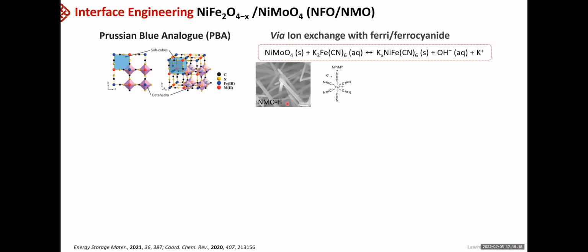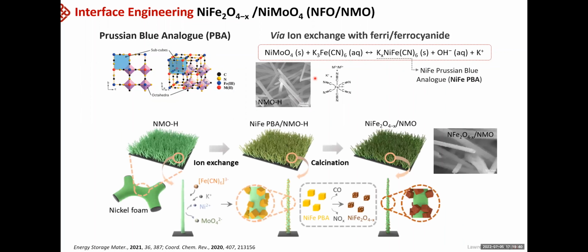So we use the nickel iron PBA as a precursor to construct the controlled interface. First, we prepared the nickel molybdate, NMO, nanowires, and we grew the nickel iron PBAs on their surface by ion exchange reaction. And then a subsequent calcination process produced the nickel iron oxide, nickel ferrite, interfaced with the nickel molybdate species. So how do we control the interface? We control the growth of nickel iron PBA, which is the precursor for our catalyst.